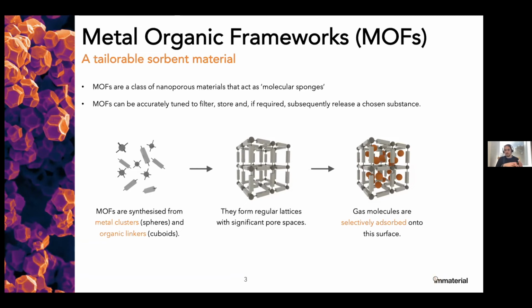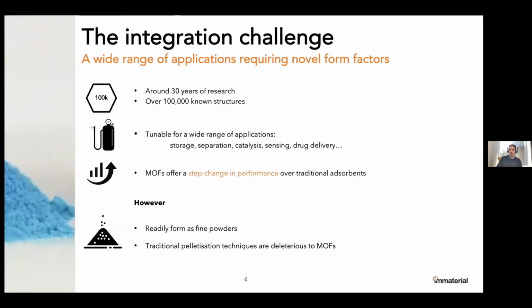The degree of tunability means that there are around 100,000 known metal organic framework structures, which compares to maybe 250 zeolite structures. And as a class of materials, they've achieved things like the largest internal surface area of any porous material. One of the challenges for metal organic frameworks has been getting them into applications, because they typically form as very fine powders. So even though they've been developed for over 30 years, and that's led to this 100,000 structures and growing every month, the fine powders are very difficult to build into the applications that we're interested in.